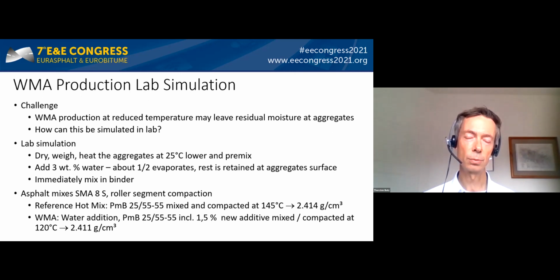Again, an SMA 8S was used and it was compacted with a roller segment compactor. The reference hot mix was produced at 145 degrees and again with the polymer modified 25-55-55 bitumen. The warm mix asphalt used the same binder but including 1.5% of the new additive and with the water addition. This mix was compacted at 120 degrees, that means 25 degrees lower. And again, we obtained equal compaction, equal density, which proved the first results.